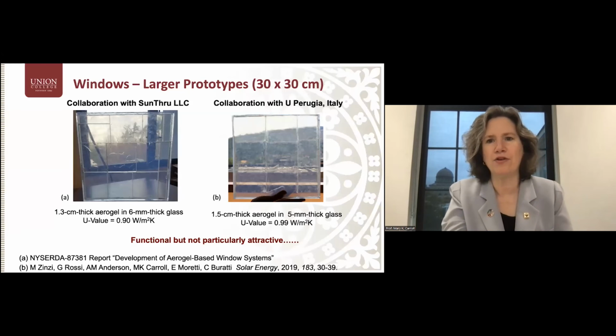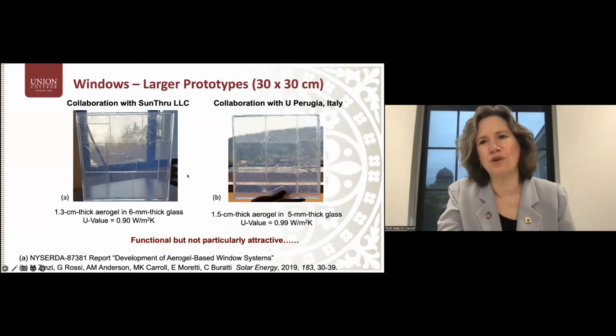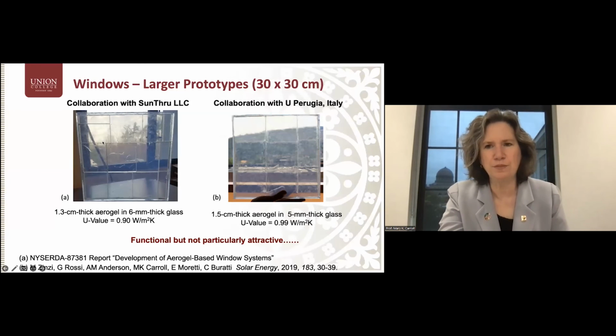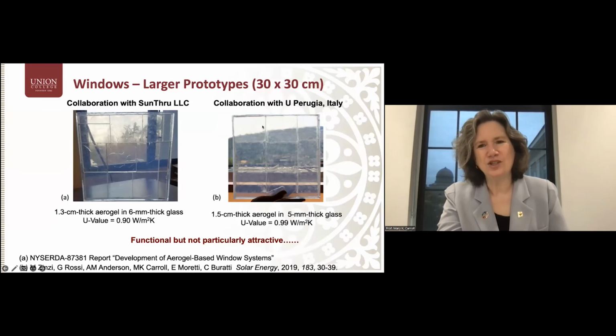And so these are 30 by 30 centimeter prototypes. They're not the prettiest prototypes. The purpose was to get them to a size where we could do some of the thermal and optical testing using standard methods. And so at this point, we were just tiling individual pieces of the gel. We can see that the U values are just below 1. And so these are functional, but they're not as attractive as you'd like them to be. You can see that they're not as transparent as we would like overall.